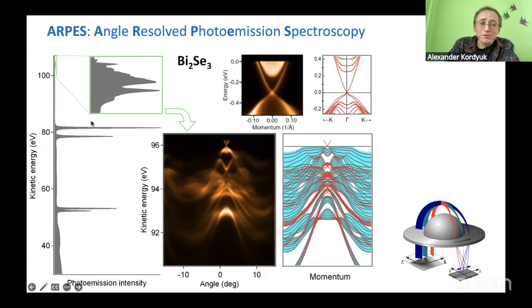So if you measure with these photons, you measure such a spectrum. In this spectrum, you see such peaks, and these peaks represent different binding energies for electrons from different orbitals, right? But it is more interesting that near the edge of the spectra, called the Fermi edge, the maximal energy of an electron which populates this solid, you have much more complicated spectra, and this is called the valence band. It does not have single peaks because the atoms interact with each other. Many atoms in the solid interact, and the spectra become widened.